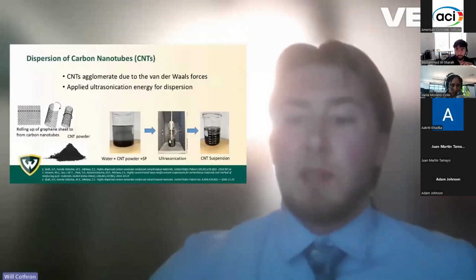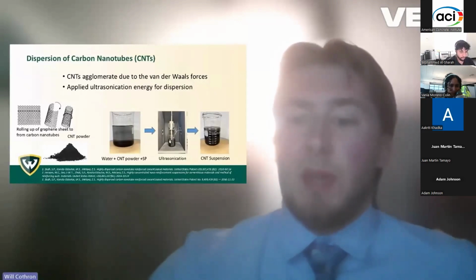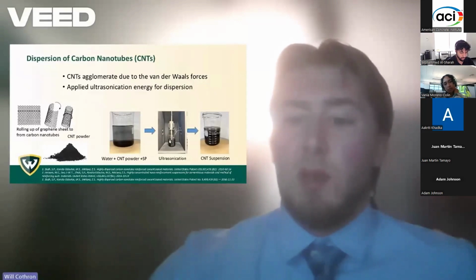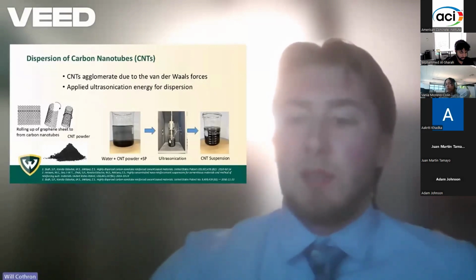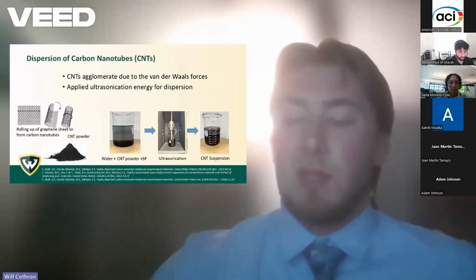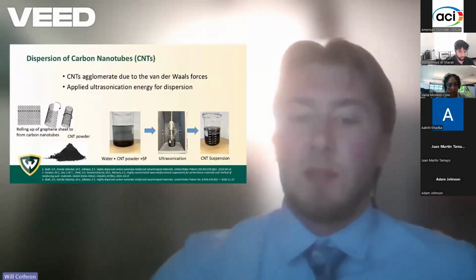We achieve this by adding CNT powder into water along with a special chemical called a surfactant, which helps separate the CNT particles. Then we applied a technique called ultrasonication, where high energy sound waves break apart the clumps, distributing CNTs uniformly in the water. The result is a stable CNT suspension that's ready to mix into concrete. Properly dispersed CNTs help make the concrete stronger, more durable, and even give it smart properties like self-sensing abilities.